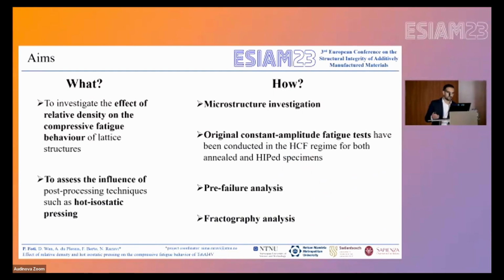So to sum up, the aims of this work were to investigate the effect of the relative density on the compressive fatigue behavior of the lattice structure, and to assess if there could be an influence of post-processing, such as the isostatic pressing, on the fatigue performance. To do this, we performed some microstructural investigation. We carried out some constant amplitude fatigue tests in the high cycle fatigue regime on both annealed and HIPed specimens. And after this, we focused on the pre-failure analysis and the fractographic analysis to understand how these components are failing.